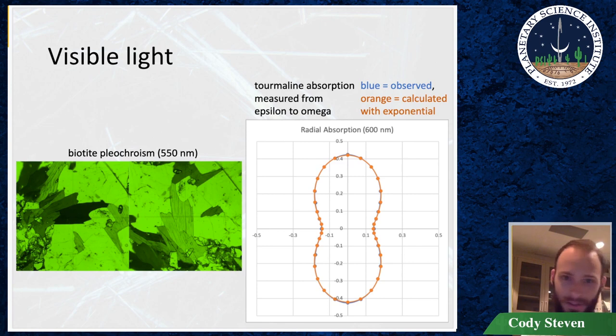So that's just pleochroism. This image is monochromatic light, though. And if you plot out absorption with orientation radially on the right, this is what it looks like. The absorption magnitude has this sort of cosine square shape, and that's characteristic of individual crystals.